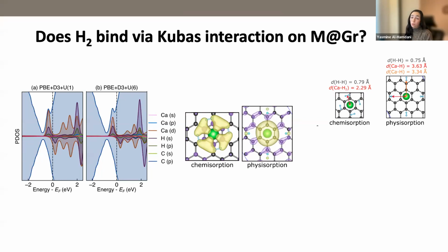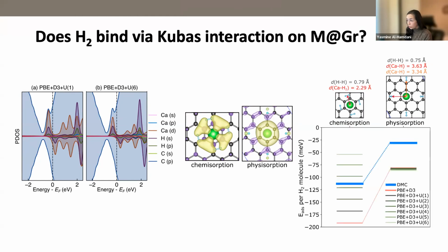Because it means that we can't really use a hybrid functional here, but at least with the Hubbard U correction, we can see what is the effect, and we see that that state still seems to be there at the DFT level. But then let's see what happens when we did QMC on the 2 orbitals that you see in the middle, on the 2 states. And so that's shown here in this figure, where you should look at the blue. So that's the DMC results.